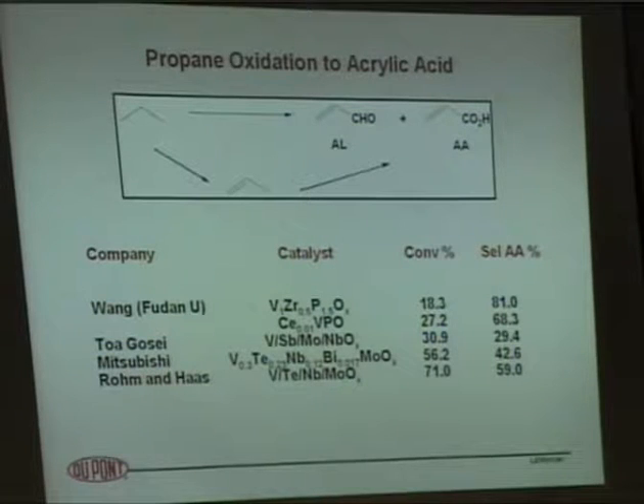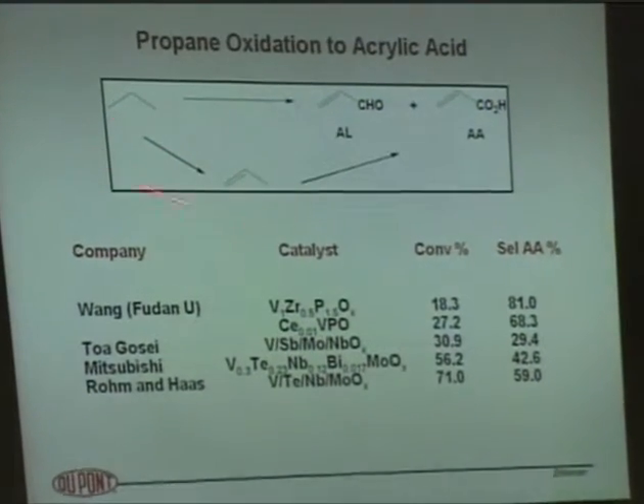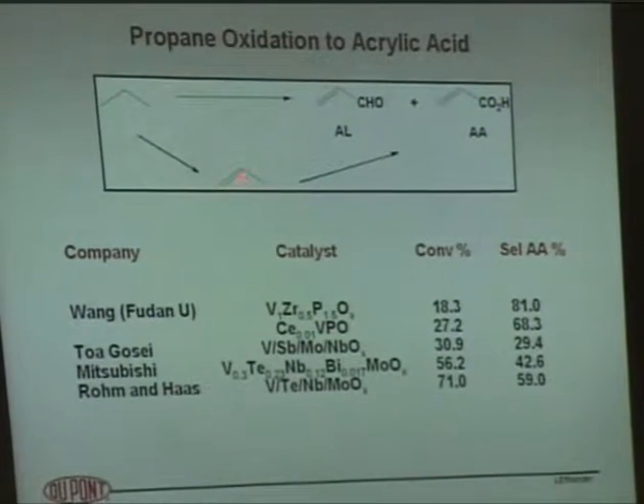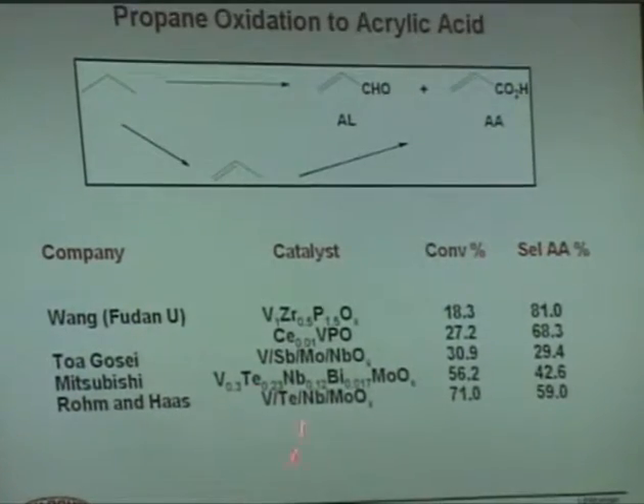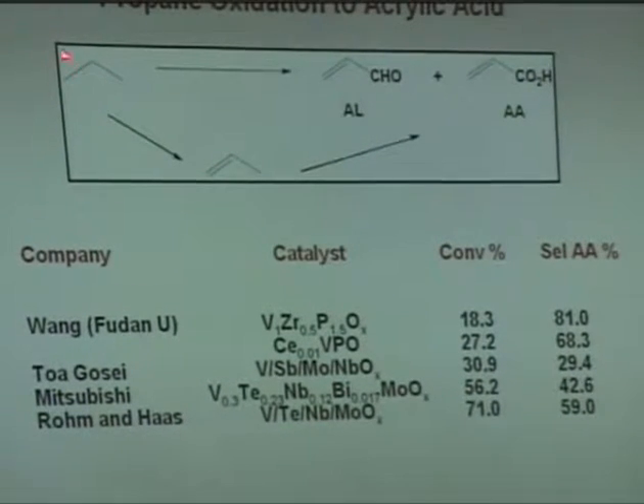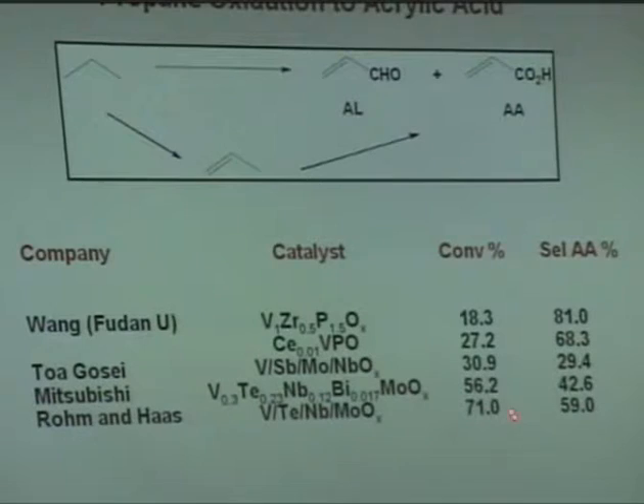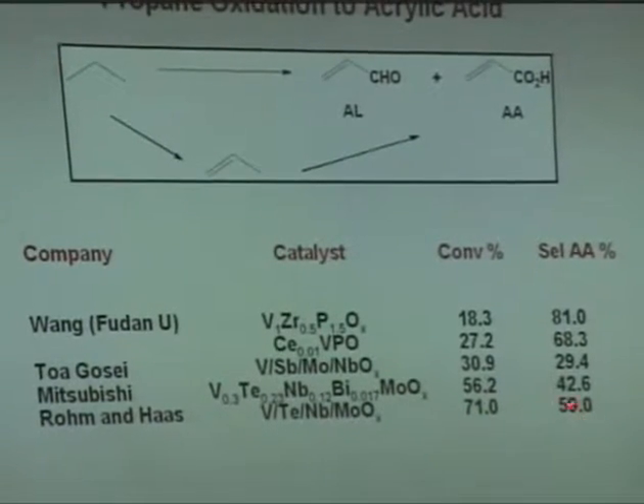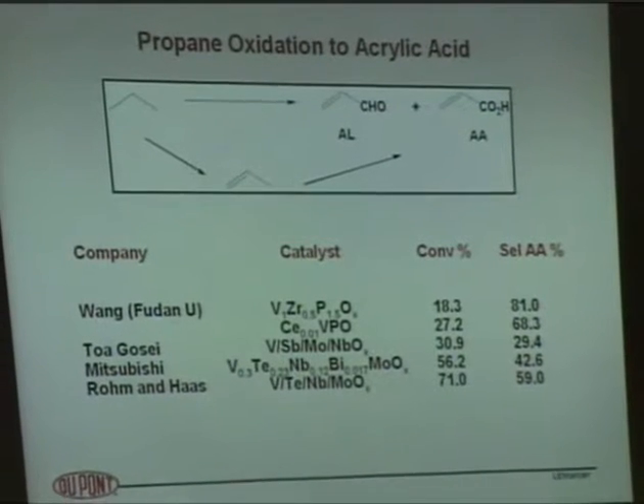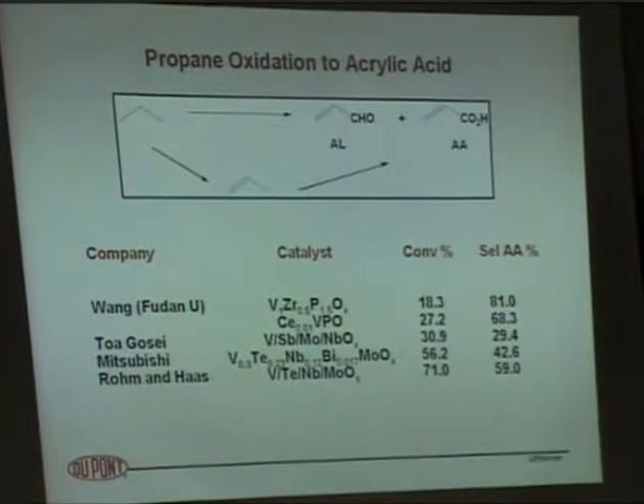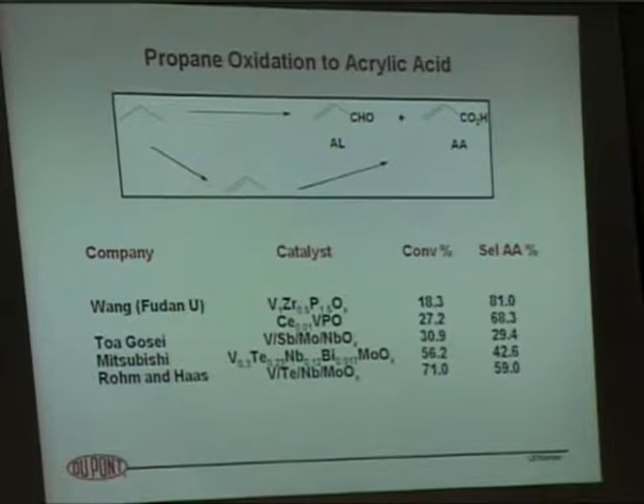Acrylic acid has been a tougher one. Typically, the process goes like this. Propane is oxidized to propylene, or dehydrogenated to propylene. Propylene then goes to a mixture of acrolein and acrylic acid, or stops at acrolein, and then a second catalyst system is used to oxidize the acrolein to the acrylic acid. Shown here are some key players in the area. Rohm and Haas has the best results that I have found recently in going directly from propane to acrylic acid, 71% conversion of propane at 60% selectivity to acrylic acid. Now, that's a really remarkable reaction. So my hat goes off to those folks, and I hope they commercialize that sometime down the road here.